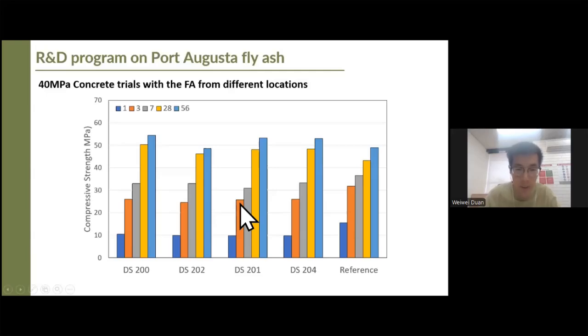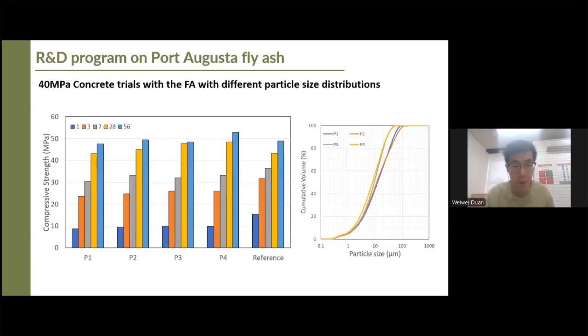All pozzolanic materials have slower strength development at early stage, but after 28 days, we could see that the strength is similar or even higher than the reference samples, which only contain cement as the binder. And we also investigated different classification parameters so that we obtain different particle sizes of the fly ash. We could see that these still have comparable strength to the reference samples, and some of the finer samples, the fly ash with the finer PSDs, even have slightly higher strength than the reference sample.